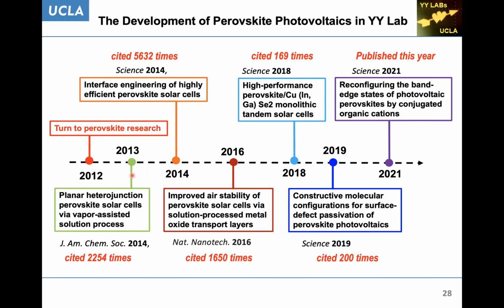In 2013, we published a paper on the planar heterojunction device. In 2014, we published a paper in Science, now cited about 5,000 times. Interface engineering is very important work; it really makes the solar cell improve. In 2016, we published a paper in Nature Nanotech on improving the air stability of solar cells by solution processing of metal oxide transport layers.